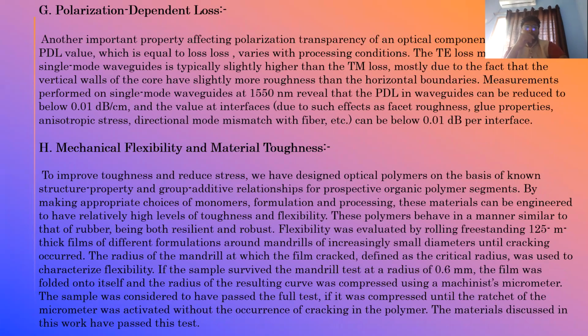Polarization dependent loss. Another important property affecting polarization transparency of an optical component is the PDL. The PDL value, which is equal to the TE minus TM loss, varies with processing conditions. The TE loss measured in our single mode waveguide is typically slightly higher than the TM loss, mostly due to the fact that the vertical walls of the core have slightly more roughness than the horizontal boundaries. Measurements performed on single mode waveguides at 1550 nm reveal that PDL in waveguides can be reduced below 0.01 decibel per centimeter, and the value at an interface can be below 0.01 decibel per interface.